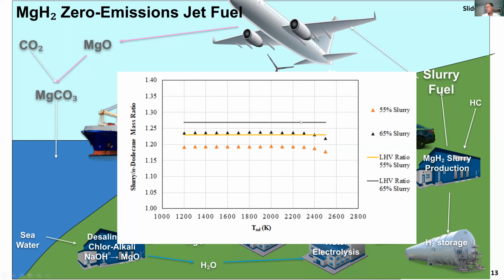That said, if we look at a comparison between the lower heating values, that does not tell the whole story because magnesium combustion is a few percent more efficient because magnesium oxide is more stable at the higher temperature, whereas carbon dioxide and water would decompose into carbon monoxide, hydrogen, and oxygen. So the actual mass ratio shown in these triangles is considerably lower than the mass ratio that you would predict just from the lower heating value energy densities of the metals.